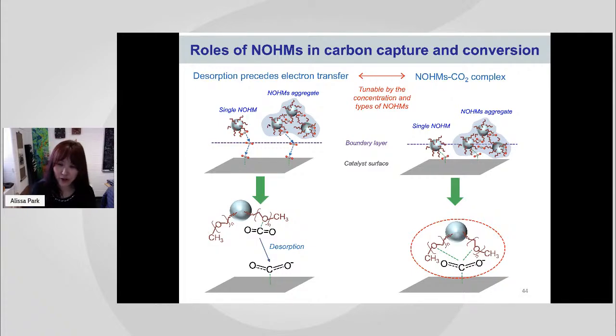Some people actually tried this with ionic liquid and saw similar results, and now start calling those materials or electrolyte additives a co-catalyst. I think at the end of the day, it tells you how you can tune reaction pathways while really improving the heat and the mass transfer and also CO2 capture and conversion rates.